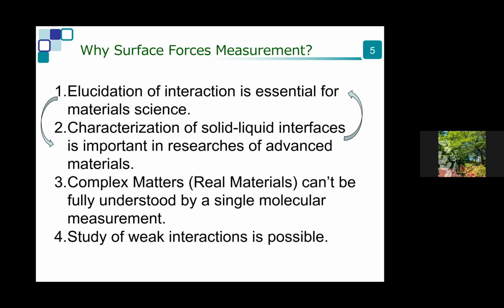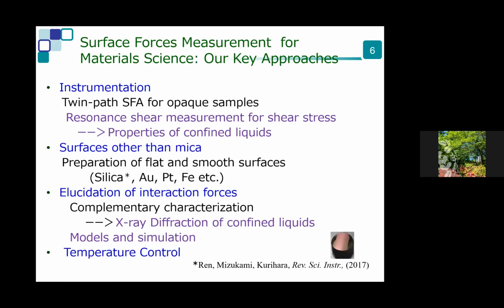And gradually, as we accumulate knowledge about interaction, I started to feel that by combining these two pieces of information we are accumulating knowledge about the origin of interaction. However, the conventional SFA is not always enough for everything if we want to study materials. So we do instrumentation, like we constructed a twin-path SFA for opaque samples. I think that is practically the only SFA for opaque samples. And for lateral force measurement, we developed resonance measurement, and using this we study intensively the properties of confined liquid.